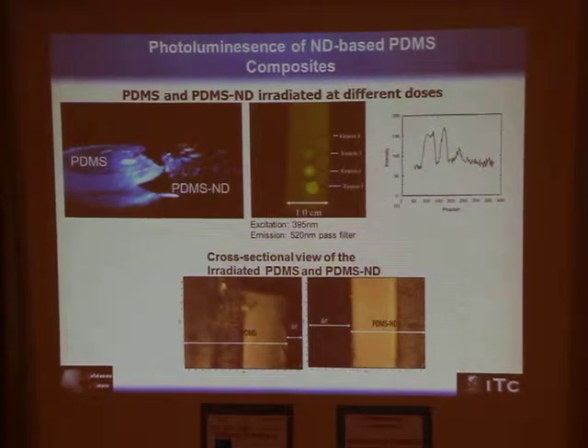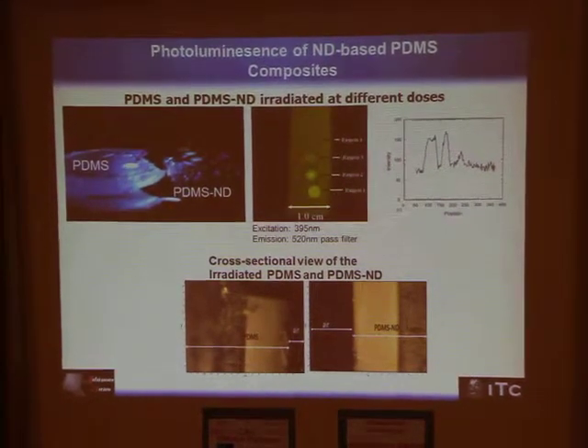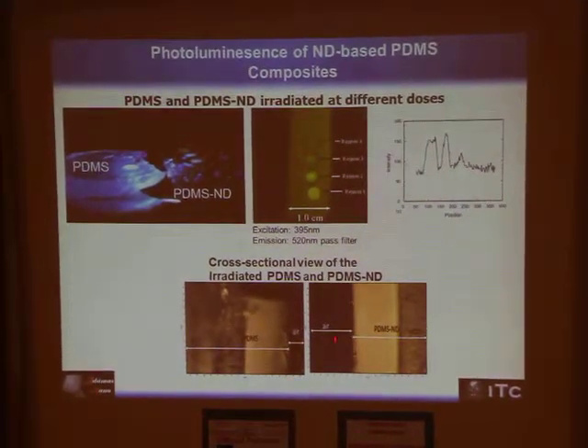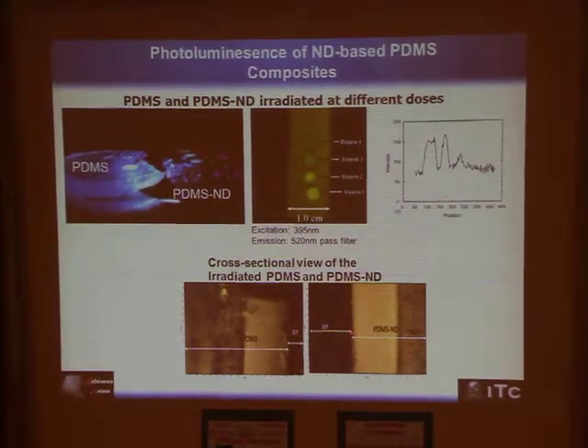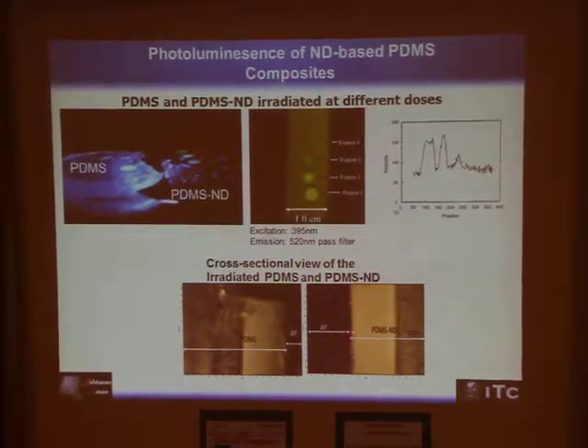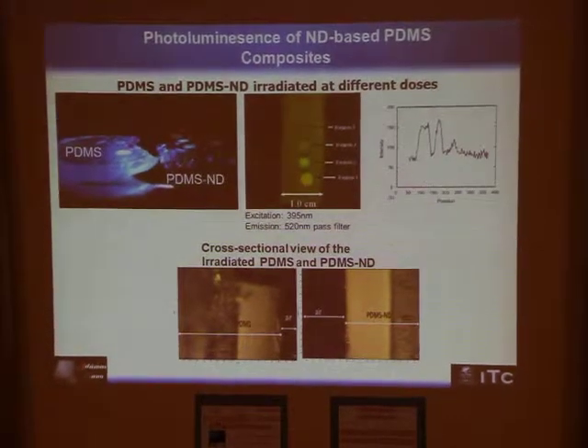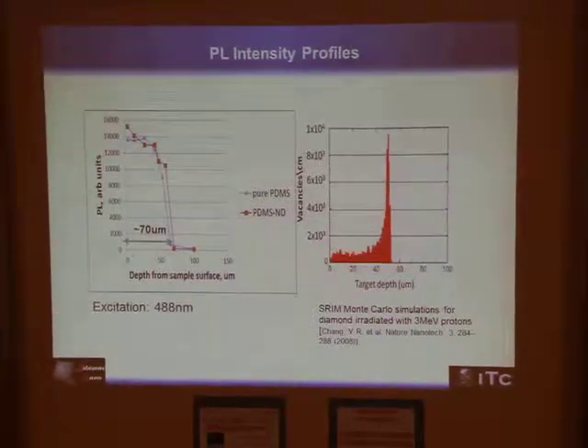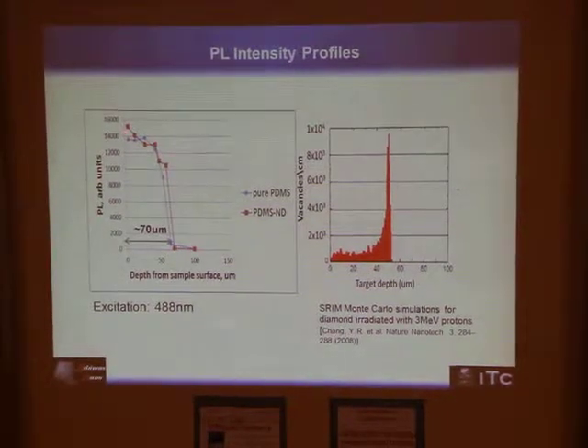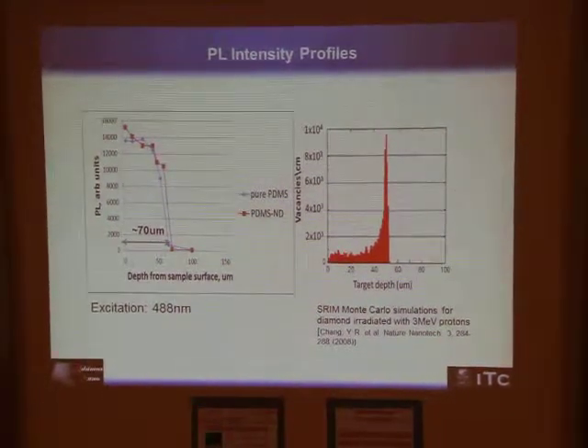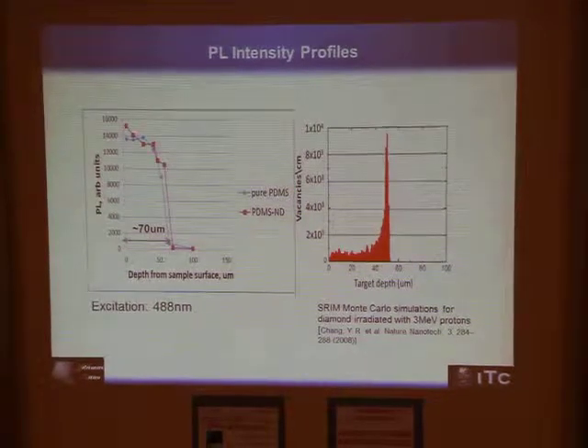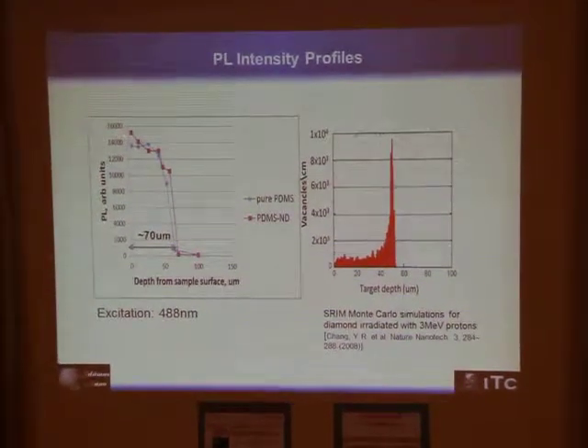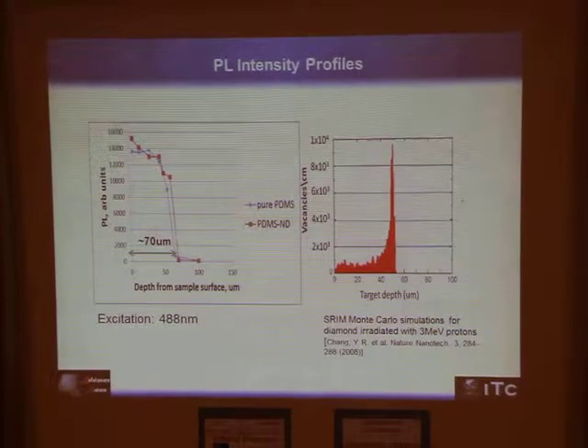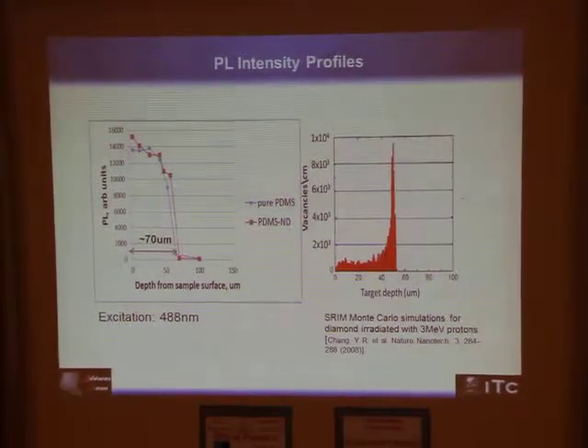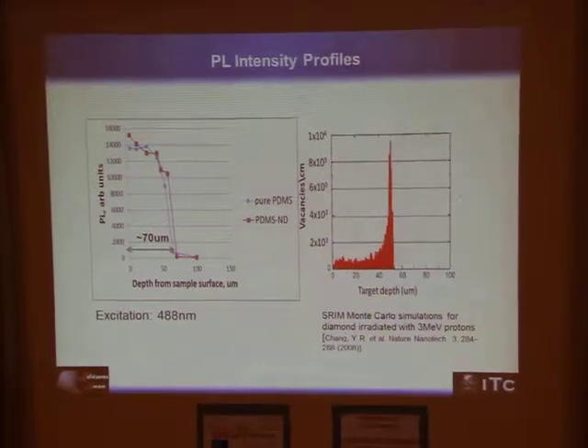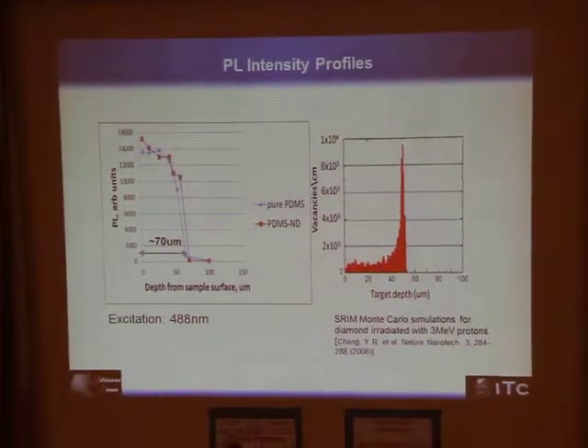This is a white light image of the irradiated composite, and Igor Vlasov took photoluminescence spectra along these lines, and they are shown on the next slide. So what you can see here is that the intensity of the photoluminescence gradually decreases for small dose irradiation of pure PDMS and PDMS nanodiamond composites, and then sharply decreases where the irradiation penetration of the proton stops.